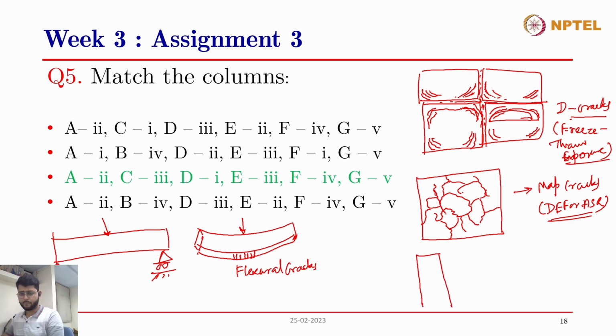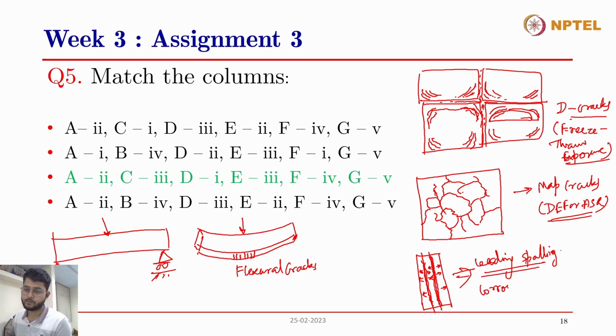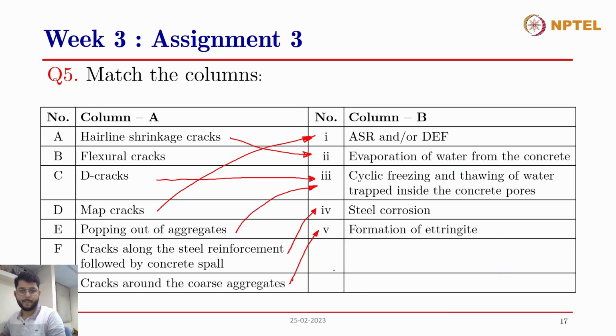So let's say this is a concrete element and there are reinforcements inside it. And when these reinforcements are corroding and these corrosion products are forming over this reinforcement, they create cracking of the concrete. So this happens along the reinforcement and essentially leads to spalling. Spalling is the explosive falling off of the concrete debris from the concrete specimens, and this is caused in the case of corrosion. So these cracks are formed on the outer surfaces along the steel reinforcement, and they result in the spalling of the concrete. And this is in the case of steel corrosion.